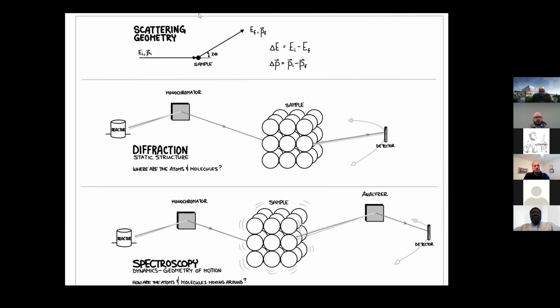And so just simple-minded ways to set up a neutron experiment are illustrated in the bottom two panels. Diffraction, you have a multi-wavelength polychromatic beam that hits a monochromator. So scattering from a monochromator, which is typically some sort of crystal like copper or silicon, will result in a very narrow band of wavelengths coming off of it. And then you scatter that from a sample into a detector, and then you can get Bragg peaks, which gives you information on the structure.